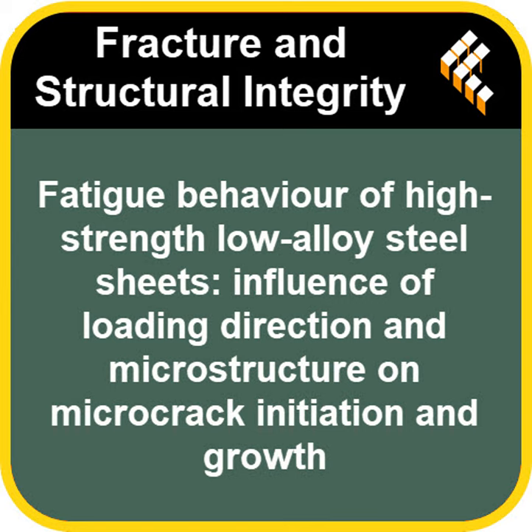So in those TD samples at high strain, the original ferrite grains were subdivided into much, much finer subgrains, maybe from 5 micrometers down to just over 1 micrometer. This hugely increased the Hall-Petch effect. And at the same time, the dislocation density just skyrocketed. So you get this powerful combination, the synergistic effect, driving that intense cyclic hardening we observe specifically in TD at high strain.